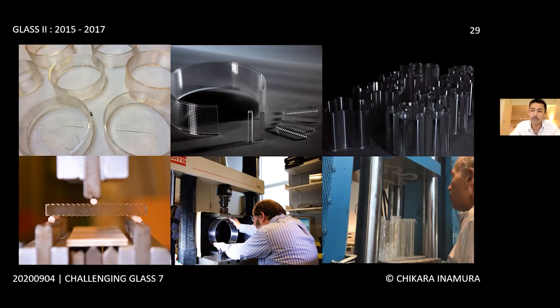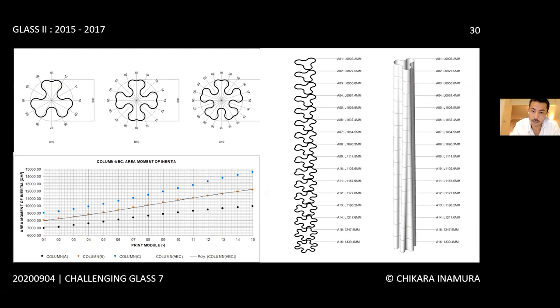This is a great value, but still much lower than the compressive strength of soda-lime glass or the critical buckling load of the fixture geometry. We conducted finite element analysis to examine this behavior and identified that the critical limit was triggered by the tensile stress that was induced by the bending at the boundary condition. We decided to build a glass column, a large-scale freestanding structure with an integrated lighting system to manifest the novelty of a material and the capability of the new additive manufacturing system.